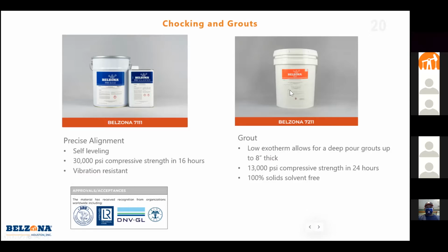And then we have our 7211. This can be used with 7111 and also by itself. The big reason for the addition of 7211 was that it provides a low exotherm, so we can really pour this thick. The 7111, you don't want to pour too thick. You couldn't do like an 8-inch pour. You can do 1/2 inch to 1 inch. So if you really have to build it thick, you can start with your 7211 and then finish with your 7111. If precise alignment isn't exactly required, you can just stick with 7211. It also has some self-leveling to it. 13,000 PSI compressive strength in 24 hours, 100% solid, solvent-free.